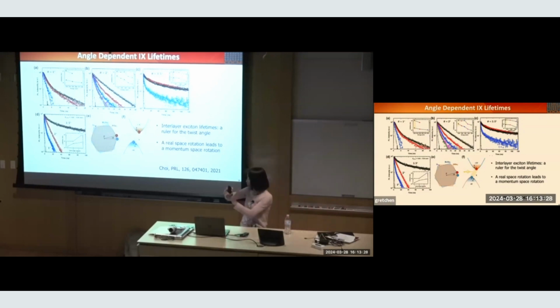When you twist the layers in real space, you're actually also twisting their Brillouin zone in momentum space. Now, these transitions happen at the K point, the corner of the Brillouin zone, right? But when I twist, I shift the conduction band away from the valence band. Now it becomes a little bit indirect. I started by saying direct gap semiconductor, indirect gap semiconductor would be very different. So I made these transitions a little bit indirect, and that's why the lifetime is getting longer. It sometimes needs a phonon involvement to make that process happen.